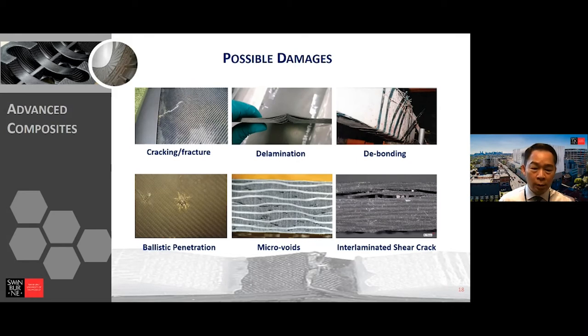Magnetic interference, infrared, and everything, because those materials are conductive, but composite is not. Okay. And then how can we detect damage? The most important thing is that you may not be able to see the damage on the surface. That is a problem. For example, this one is very nice. You can see the crack, but if there's a painting on the surface,